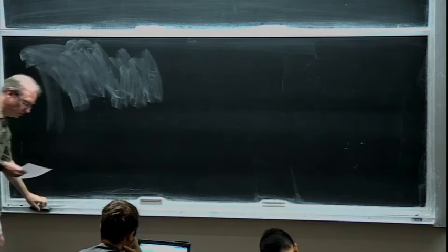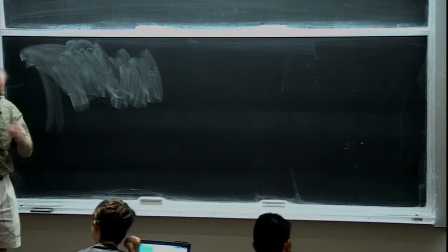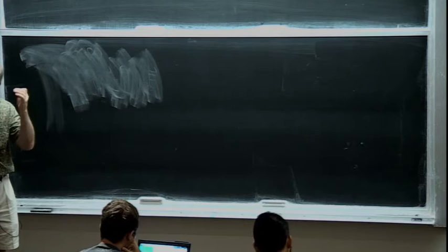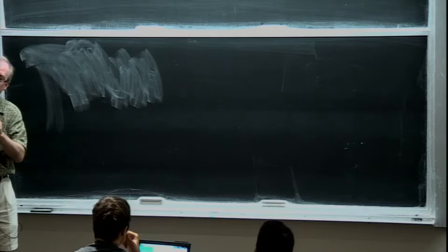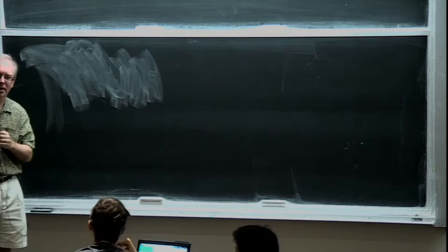What sort of magnitude does it have in graphene? What size splitting does it make? It's small. People have argued about whether it's really small or really, really small. The numbers, I think I remember, it's a question of whether it's microvolts, or maybe tens or hundreds of microvolts, something like that. So the question is whether it's Kelvin or millikelvin. That has yet to be measured.